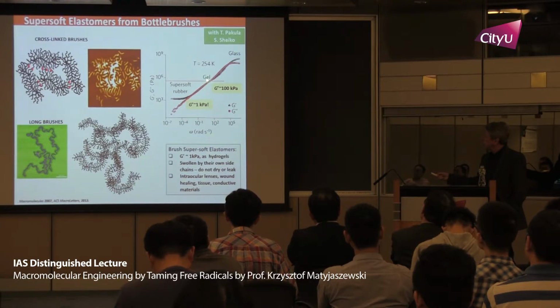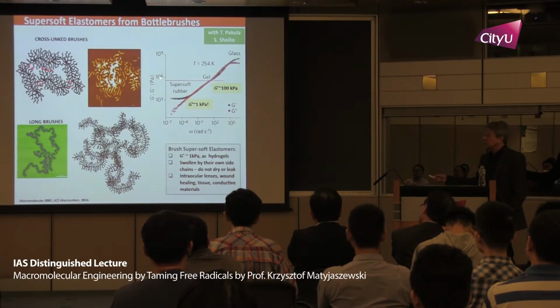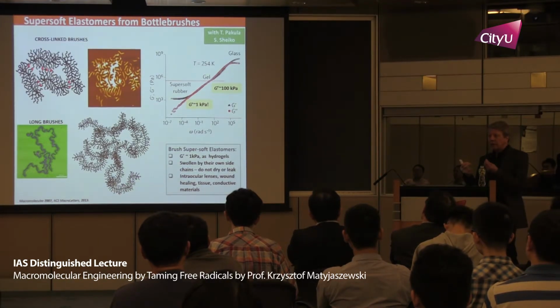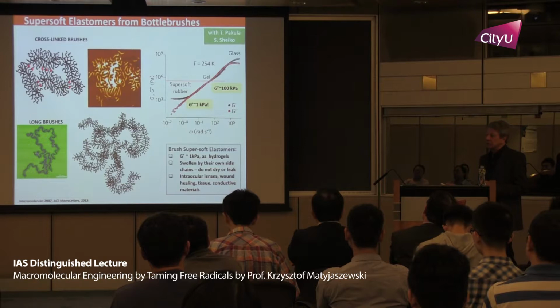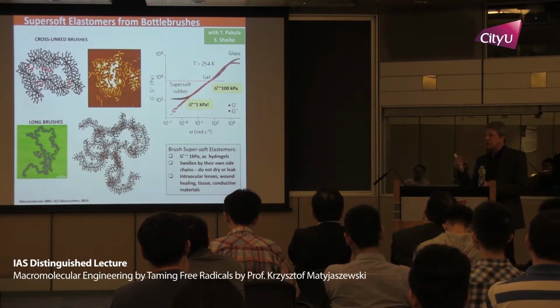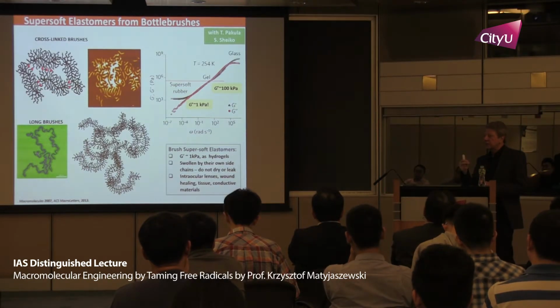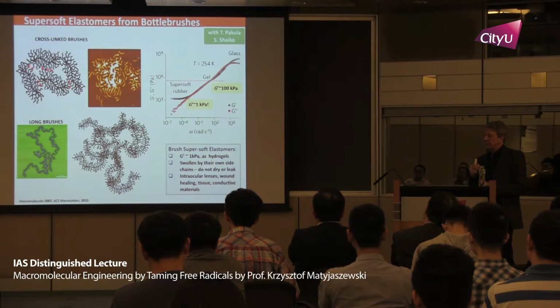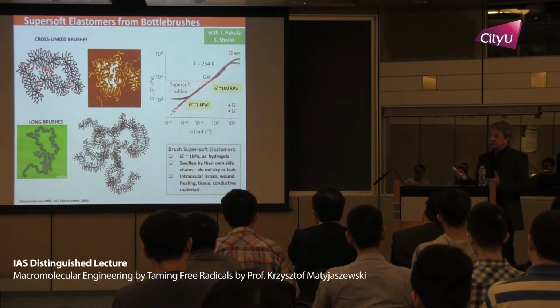But if you go to higher and higher molecular weight, this extends, or you can crosslink it, and this is typical rubber. If you think about a rubber band, it has a modulus of approximately 100 kilopascal, which is 10,000 times softer. But we wanted to make even softer material. So if I ask you what materials you know which are 100 times softer than rubber, typical answer is gels or hydrogels.